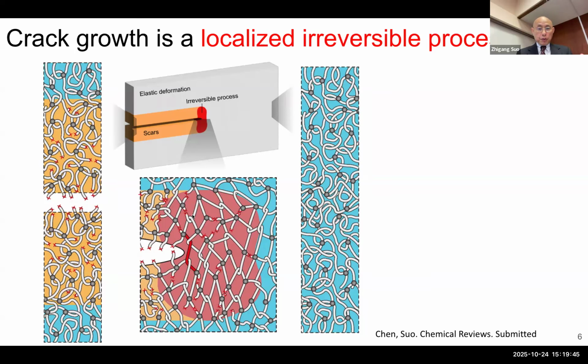Break chains. Also, you have this non-covalent interaction between chains that causes friction and viscoelasticity. You don't break chains here, but there's a large region where you have a viscoelastic deformation, which is dissipative. It's irreversible. So this scale, this red scale, this dissipation zone is still small compared to this elastic body.